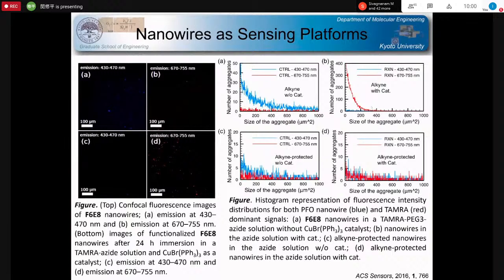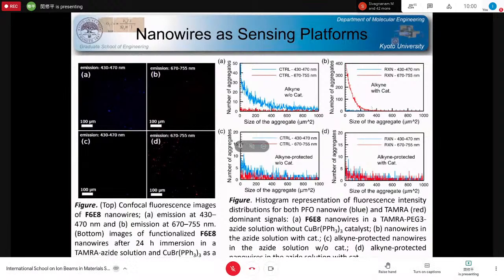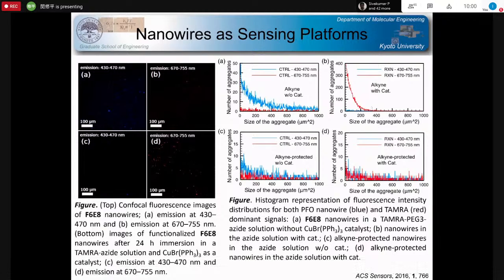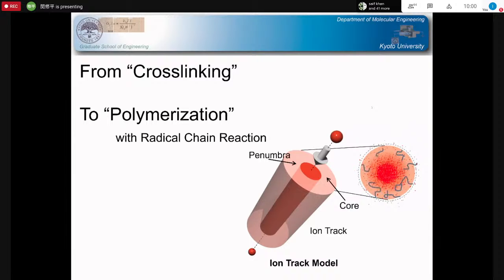Once we irradiated the sample at one segment with ultraviolet light, the ultraviolet light was absorbed, and the harvested energy at one part of the nanowire was transferred to another part of the nanowire, which exhibits red light emission where the functional unit was embedded. So, as displayed in this view graph, the energy was transferred from one segment to the other segment. And such sensing materials were also realized by the single particle nanofabrication techniques developed by ourselves.